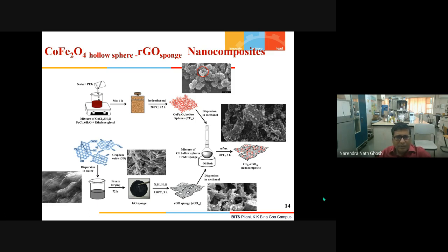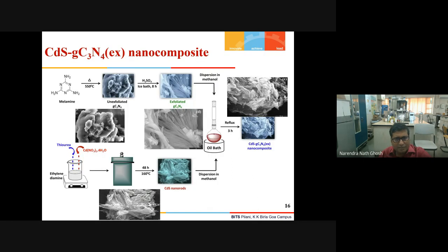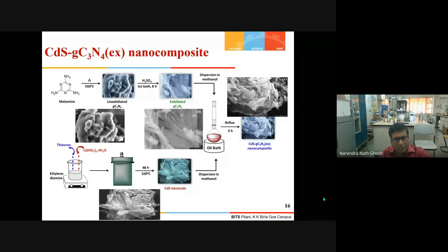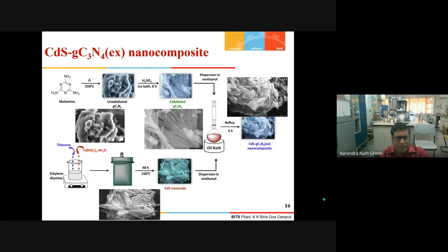Next one, please. Another one is cadmium sulfide and exfoliated graphitic carbon nitride. Making graphitic carbon nitride is very easy. One of the methods is to take some amount of melamine, treat it at 550 degrees in a furnace, and you will get some amount of graphitic carbon nitride.